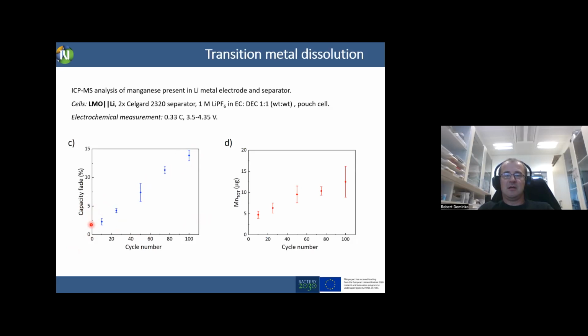And you can see here that there is a linear decrease of the capacity with the cycling when you are using lithium manganese spinel, while manganese dissolution is really the highest at the beginning, but then it's not completely stopped, the dissolution is decreasing, and I see this a little bit more like a logarithmic function. But anyway, if we correlate the quantity of dissolved manganese that we detected here and capacity fade, we can see that